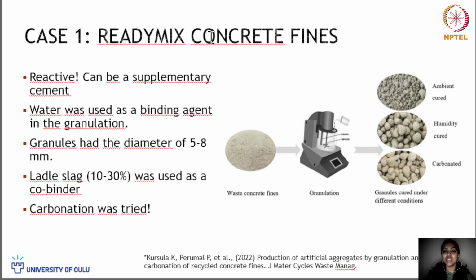So here you see the ready mix concrete fines as case study 1. Like I said, this is relatively fresh, so it still has the reactivity, and it can easily be used as a supplementary cement. Water was used as a binding agent in this granulation. We didn't go for any special grinding aid or granulation liquid, because this material itself was reactive, so we just need to add some water there.